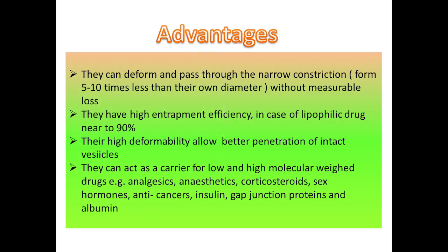Advantages: they can deform and pass through narrow constrictions. So it can pass through constrictions 5 to 10 times less than their own diameter without measurable loss. They have high entrapment efficiency in the case of lipophilic drugs, near to 90%. Their high deformability allows better penetration of intact vesicles.